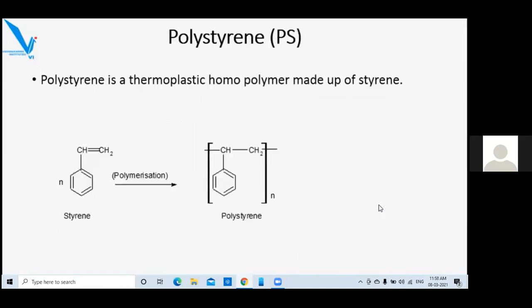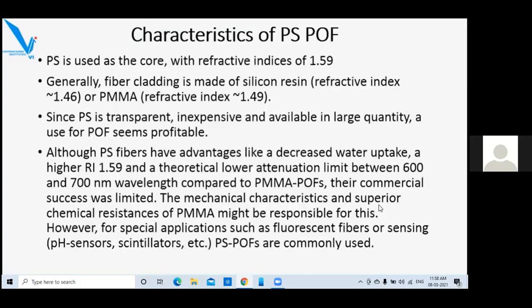The second material used here is polystyrene. Polystyrene is a thermoplastic homopolymer which is made up of styrene. Polystyrene is used as a core with refractive index 1.59. Generally, the fiber cladding should have a lower refractive index, so we can use silicone resin with a refractive index 1.46 or polymethyl methacrylate with a refractive index 1.49. Since polystyrene is transparent, inexpensive, and available in large quantity, use of it in polymer optical fiber seems to be profitable.